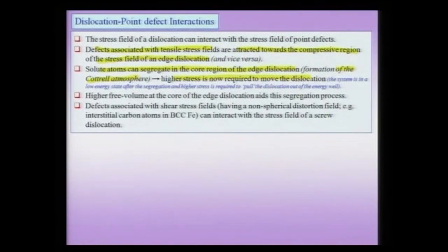Because the segregation means the system has gone into a lower state of energy, and if I have to pull the system out of this energy well then I have to apply a higher stress. To move a dislocation we need to apply shear stresses at the atomic level. The dislocation core — especially for an edge dislocation in the region just below the half plane — is a region of extra volume or free volume, and therefore that region can nicely accommodate certain small interstitial atoms compared to the normal lattice where a higher energy is required.